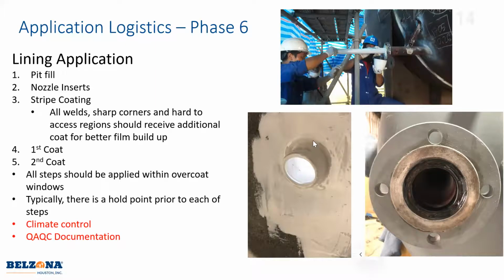As you can see here, he stuck it in from the outside and it protrudes a little bit. Once it's dry, you can cut it flush with the vessel and then taper it and bevel it down to the flange or to the vessel wall. So that gives you 100% coverage of the nozzle. Nozzles are an area that tend to be the failure points. So this is a system that increases the reliability tremendously.